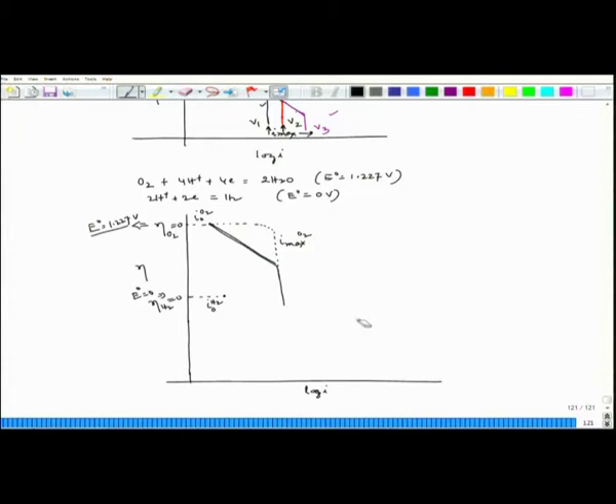Now, as it goes towards the cathodic polarization regime and is polarized, the overvoltage increases gradually. The hydrogen reaction also has its own activation polarization. If that one moves like this, then because once I max is reached for oxygen reduction, it will fall rapidly, almost perpendicular to the log I axis, and then it will experience the activation polarization of hydrogen reduction.